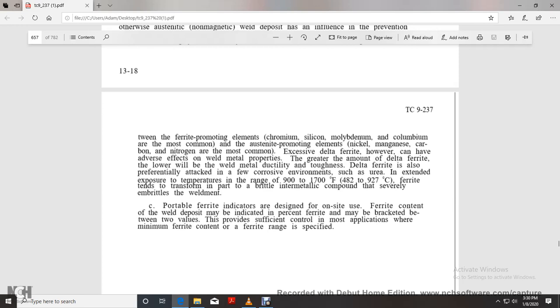Excessive delta ferrite can have an adverse effect on metal properties. The greater the amount of delta ferrite, the lower the weld metal ductility and toughness. Delta ferrite is often preferentially attacked in a few corrosive environments. Extended exposure in the temperature range of 900 to 1700 degrees Fahrenheit causes ferrite to transform in part to a brittle intermetallic compound that severely embrittles the weldment.